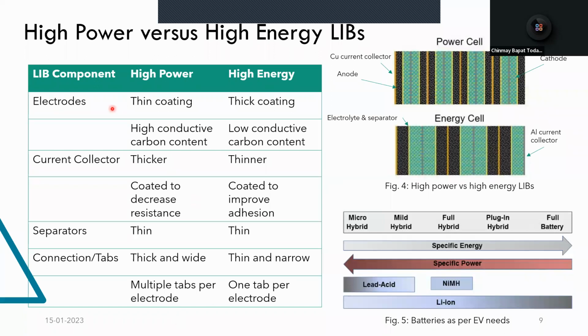So the electrodes in the high power cell are thin and they have higher conductive carbon content to reduce the internal resistance. The current collectors are thicker and also coated to reduce the internal resistance. With respect to connections or the tabs on these batteries, they are thick and wide, and there are multiple tabs per electrode for high power cells. And in high energy cells, the electrode tabs are thin and narrow, and only one tab per electrode is sufficient.